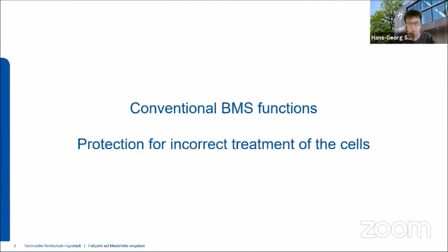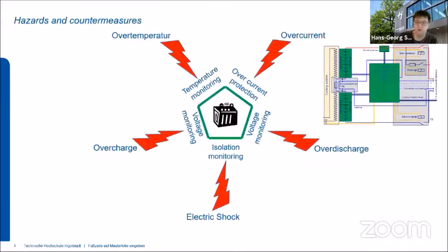So at the beginning, I want to start with conventional BMS functions, which protect the battery from mistreatment or incorrect treatment of the cells. So we have 5 different threats to a battery system and to the cell. Battery cells will behave rather dangerously if you overheat them. You have an inflammable liquid inside the battery, which is an organic carbonate, which can catch fire if you overheat it. You have a very strong reductive agent as the negative electrode and a very strong oxidation agent as the positive electrode in close proximity to each other, just separated by a thin sheet of separator, which is typically some polyethylene polypropylene mixture, and this separates these two very reactive agents from each other.